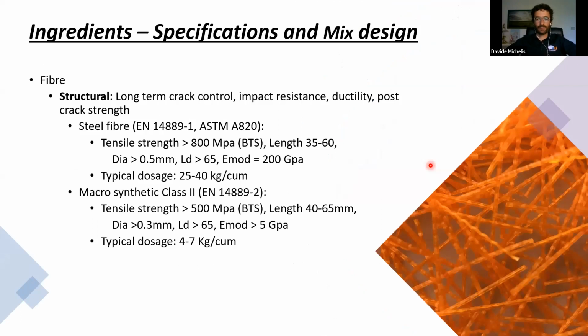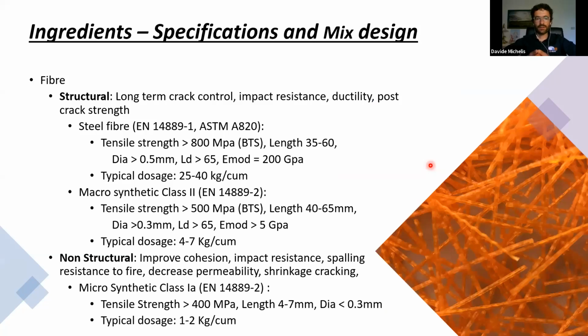Fibers are another ingredient. We can find structural and non-structural fibers. Focusing on structural fibers, there are mainly two groups: steel ones with a dosage that can vary from 25 to 40 kilograms per cubic meter, and the macrosynthetic fibers, whose dosage can vary between 4 and 7 kilograms per cubic meter. So there is a big difference in terms of dosage, but very interesting in terms of performances. The non-structural fibers are mainly used for anti-spalling phenomena, and they are used in a dosage between 1 and 2 kilograms per cubic meter.